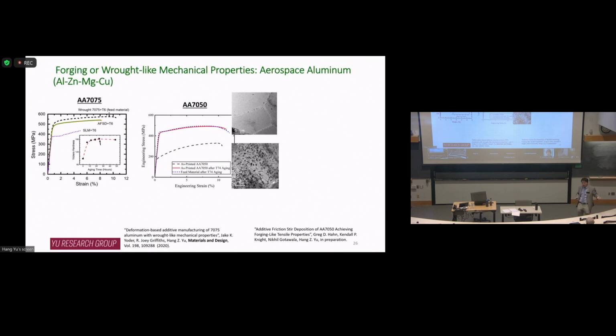Here, the story is similar. You don't have to change any chemistry or composition or add nanoparticles. Just use the engineering feedstock and you can get good properties. Here, of course, I'm trying to show you the difference between the as-printed material and the aged material. The as-printed material is of low strength because there's a complex precipitate evolution during the process as well. Essentially, during the cooling process, there are overgrown precipitates, so you can see large precipitates, much larger than the ideal case, which will give you a peak strength.